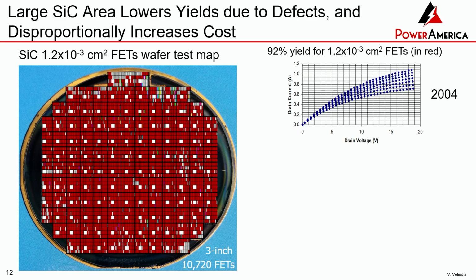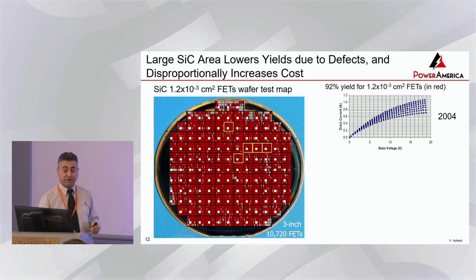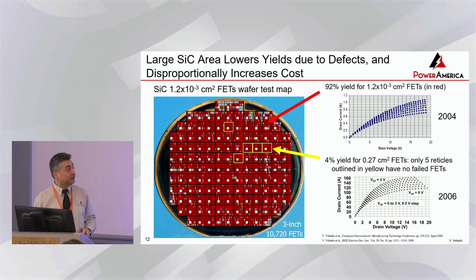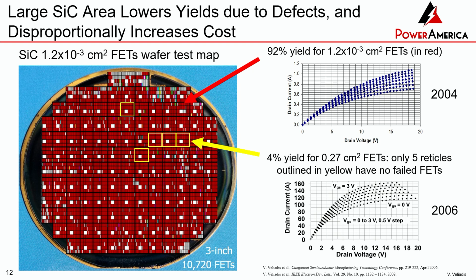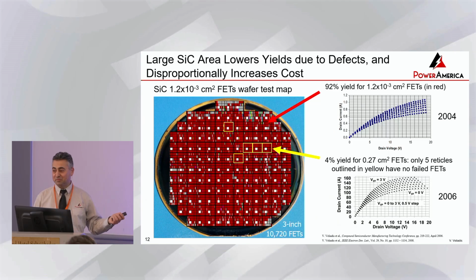And this type of device went into a military aircraft radar system. But when I tried to make larger devices, I wanted the device to be that whole square as far as area is concerned. And I was only able to find 5 squares there that didn't contain a failed device. So when I made the larger area devices, where I had to have every square without a defect, right? My yield went all of a sudden from 92% to 4%, okay? So it's a very steep road getting to high yields and making large devices. Obviously, I wrote a paper about that. I conveniently omitted the yield aspect, but pointed out the benefits in the large area.